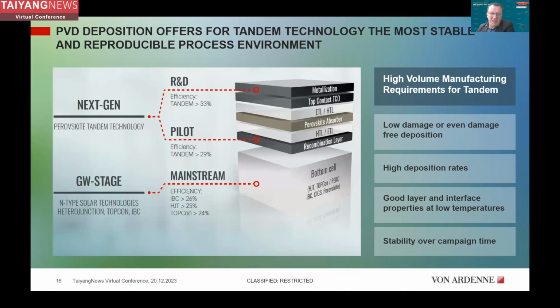And you're familiar with this stack. On gigawatt stage, the mainstream bottom cell is very well implemented, either silicon-based or even thin film-based technologies, but on top you have to do the additional coatings, either directly on top of the bottom cells for two-terminal, or you coat all these layer stacks on glass to apply the four-terminal approach. And we believe that part or most of the layers which you should coat on top, so the recombination layer, the HTL, the perovskite absorber, the ETL, and a top TCO top contact, or even the metallization, should or can be done with PVD processes.